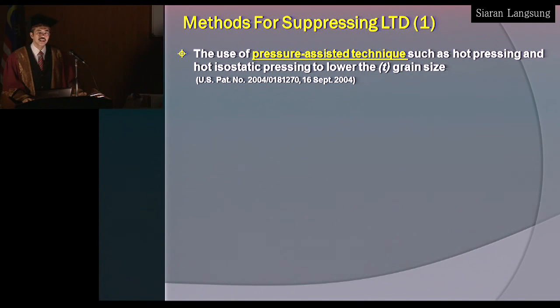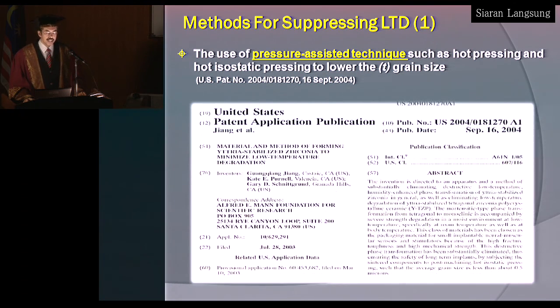So what are the methods being adopted by researchers and engineers in order to suppress LTD? One of the famous methods is to apply pressure-assisted techniques such as hot pressing or hot isostatic pressing to lower the tetragonal grain size. For those who are not familiar with this technique, it is simply a consolidation technique whereby temperature and pressure are applied simultaneously to consolidate the material. As a result, we are able to consolidate the material at low temperature because it's pressure assisted, and therefore we can suppress grain growth. And so we are able to retain fine tetragonal structure.